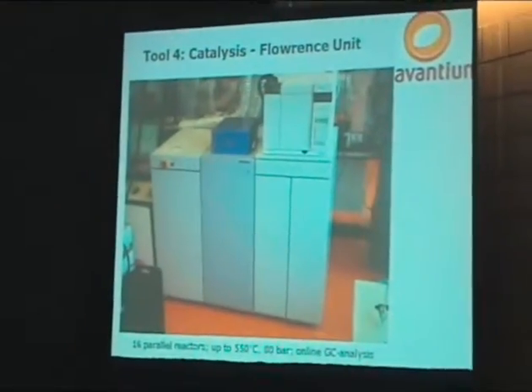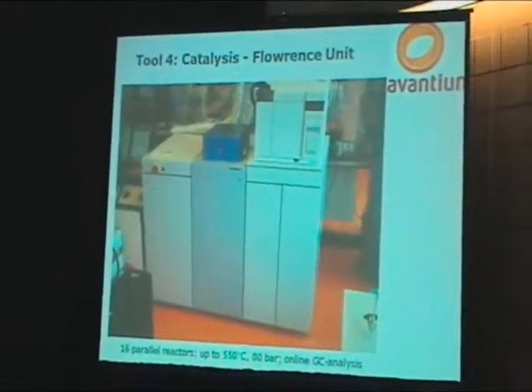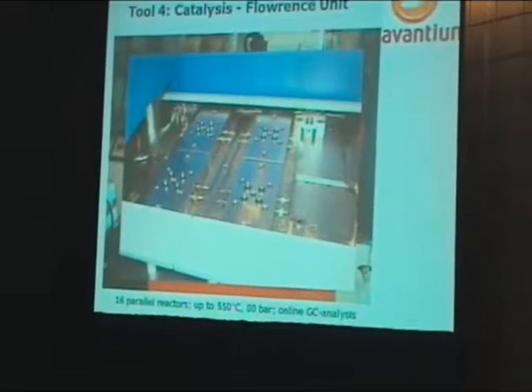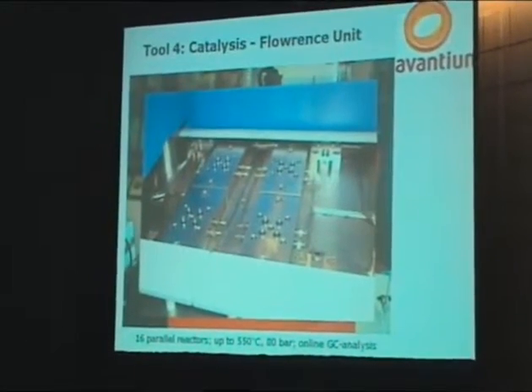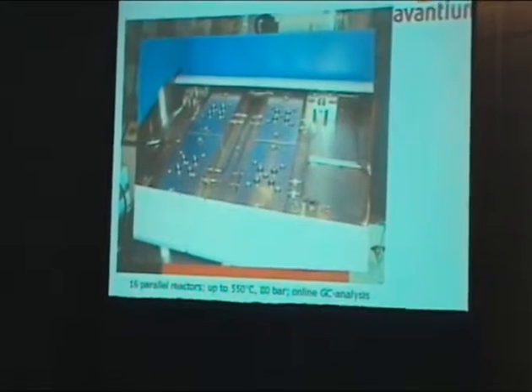And the fourth one is, of course, catalysis. We need catalysis. This is from Avantium, a so-called Flowrence unit, with these typical conditions, up to 550 degrees centigrade at 80 bar, also with syngas and online GC analysis. The 16 parallel reactors are in 4 blocks that we can heat independently, so we can select 4 different temperatures, but within one block the temperature is uniform. So that's about the tools.